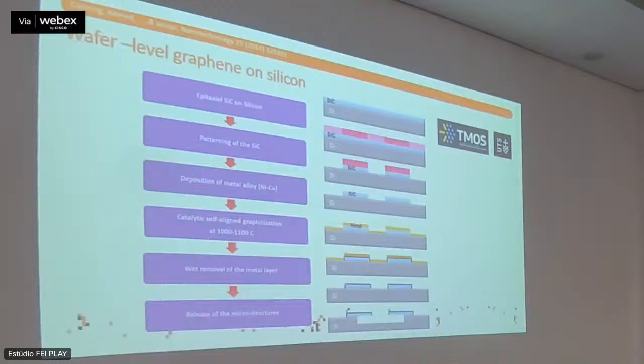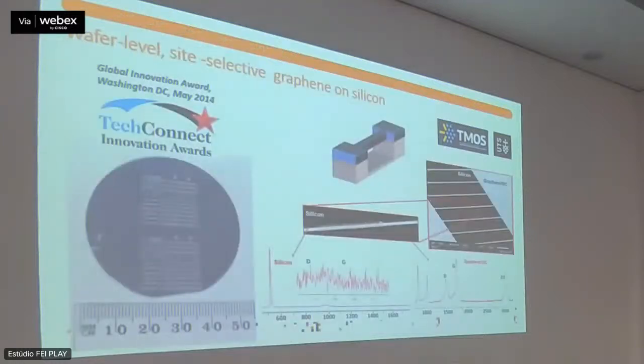So this is really very good, because you can imagine that instead of having to transfer plate by plate or having to pattern it once you've built the plate, you basically can do this already at wafer level, and this will also conformally cover and coat all of the silicon carbide structures. And this was one of our first examples where we did this, again on a small wafer just as a demonstration, where silicon carbide bridges were suspended on top of silicon.